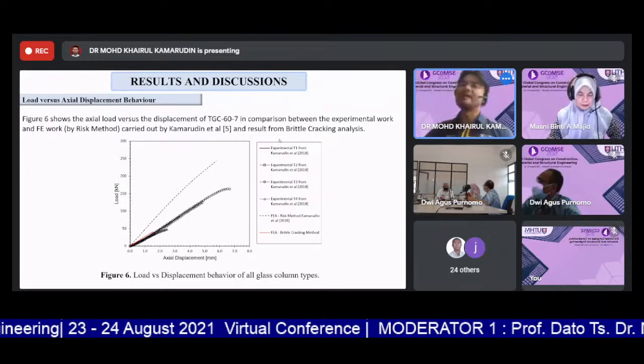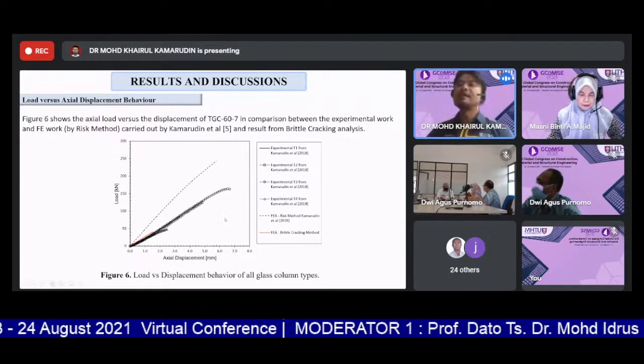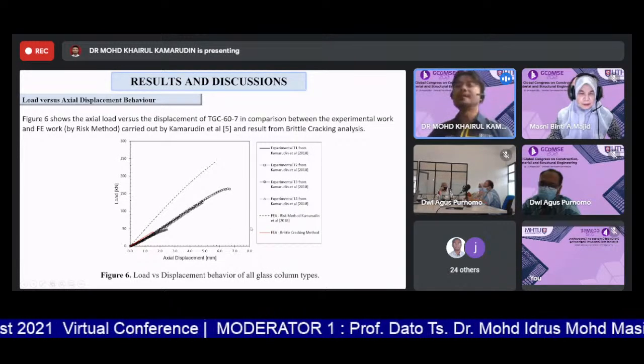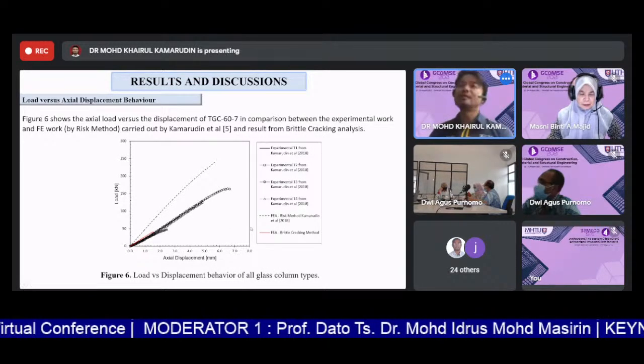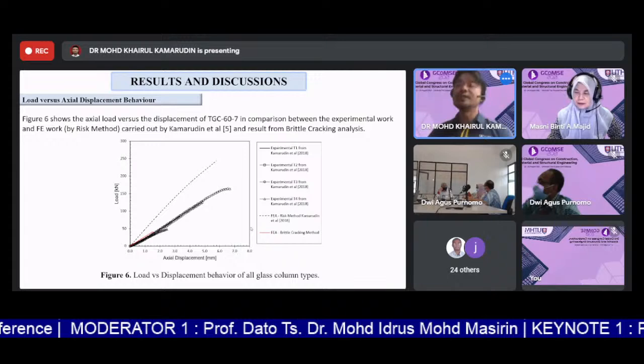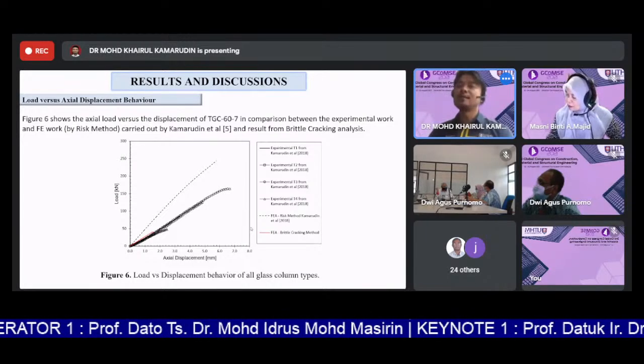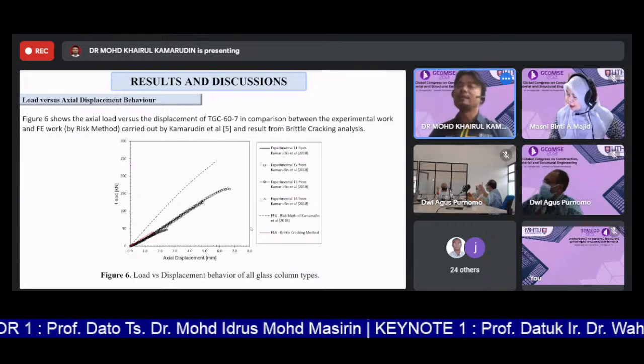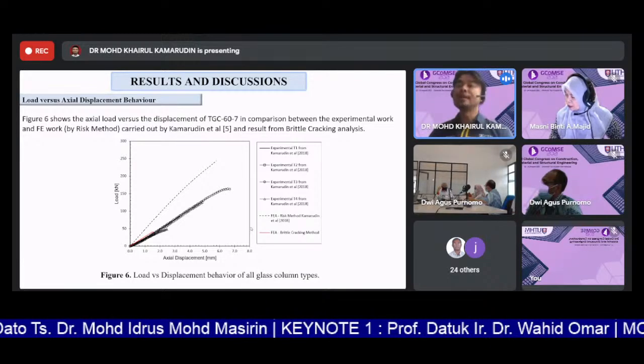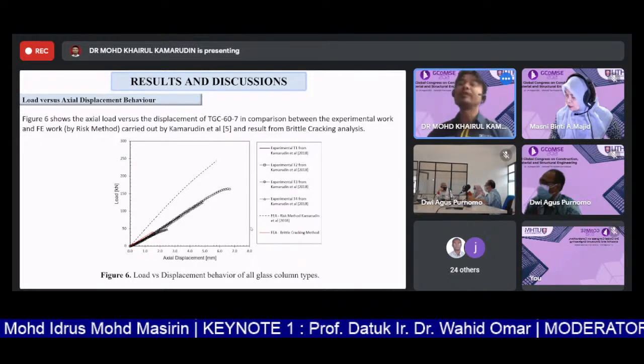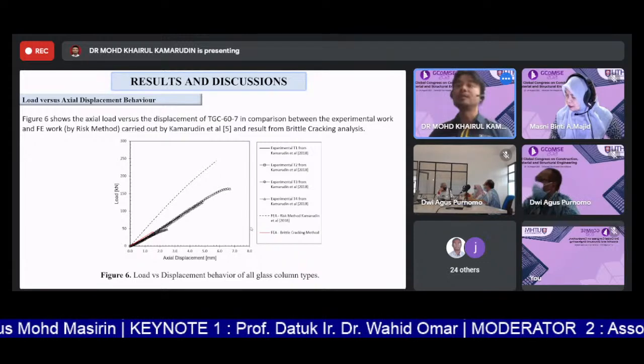But somehow we wanted to share this information, that by using the brittle cracking method we managed to capture quite an agreeable, correlated result compared to the experimental work.